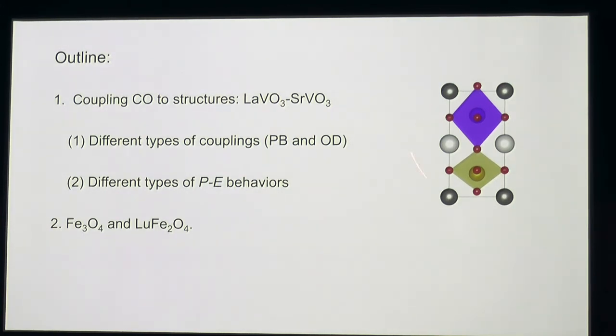In the beginning, based on the superlattice, I will introduce two kinds of lattice distortion coupling to the charge ordering, polyhedral breathing and off-centering displacement. Based on the types of the lattice distortion coupling to the charge ordering, I will classify all the charge ordering materials into two different categories. And next, I will demonstrate that the polarization dynamics of such two different types of charge ordering systems are dramatically different. And finally, we will apply our theory to explain the experimental observations in magnetite and lutetium ferrite.